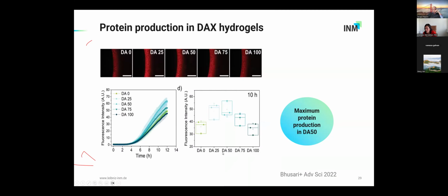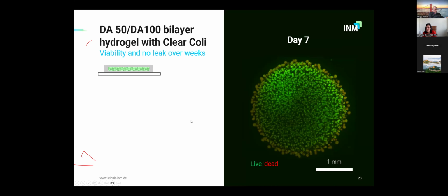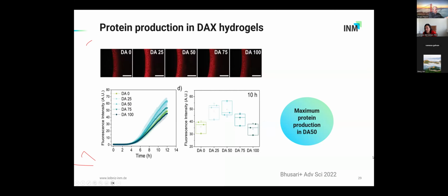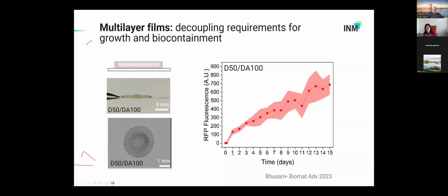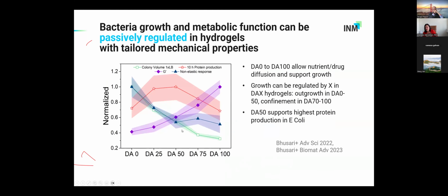If we quantify growth inside, then we see that this keeps viable and also no leaking over weeks. We can then check how growth runs, and we see that growth happens in the bacteria with intermediate concentrations and also protein production. So we can generate systems in which we can maximize production at certain polymer conditions and minimize growth, or maximize growth depending on which composition we use at others. So all these parameters we can control by that. We can control growth, we can control production, we can also control outgrowth by changing the compositions.